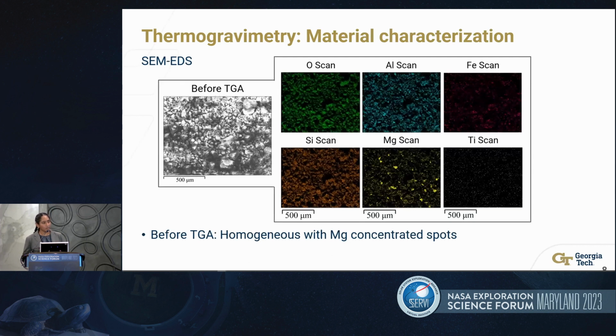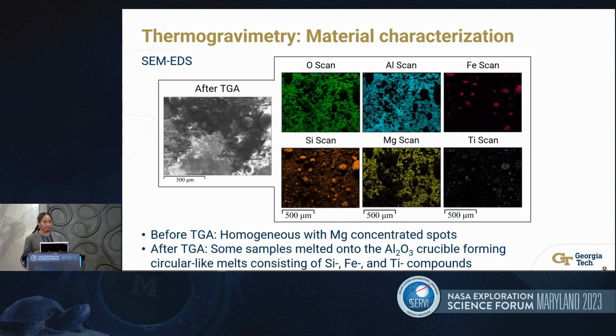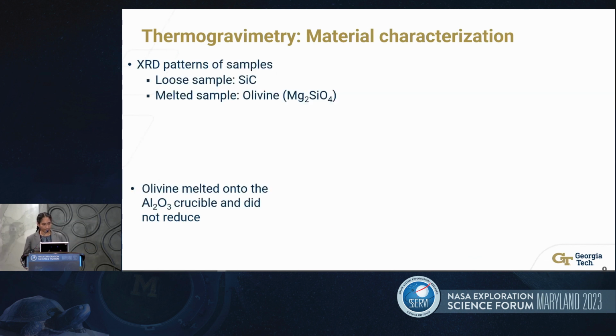The TGA sample was then studied using SEM and EDS. Before TGA, the sample was homogeneous, with the magnesium scan showing concentrated spots throughout the sample. After TGA, some samples were loose and some formed circular-like melts on the crucible. EDS showed that these melts consist of silicon, iron, and titanium compounds. The aluminum scan is contributed by the alumina crucible, and the silicon and magnesium scans showed that some sample was also directly sticking to the crucible.